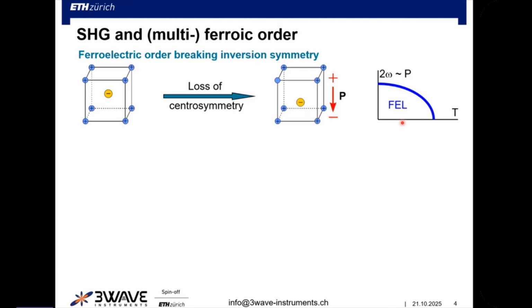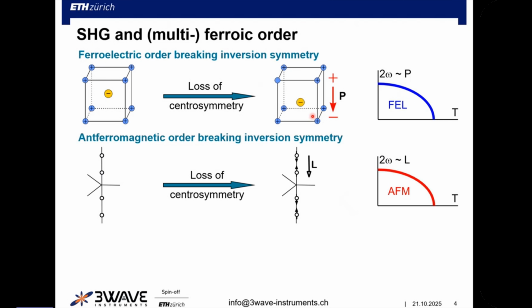So right when this happens, when your material becomes ferroelectric, you see the emergence of this frequency doubled signal out of zero background. So it's a higher order weak process, but it's background free. So you can crank up your detector and you see it. So strong light or intense light is not always good if it's on the background of other intense light, but here it's background free. And that doesn't only work for electric order, it also works for magnetic order.